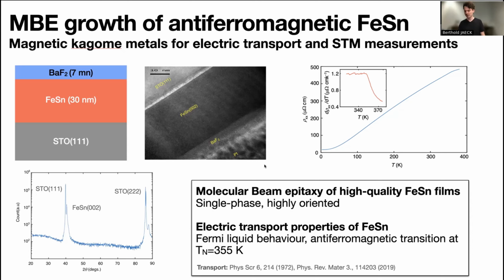At a very fundamental level, when we make a simple Hall-bar device and first study the longitudinal conductivity, we find that this material behaves like a fairly good metal with a reasonably high residual resistance ratio, and we can also pick up the antiferromagnetic transition at the Néel temperature at about 355 Kelvin. Without going too much into the details of these materials characterizations, we find that both the basic electronic and magnetic properties are very consistent with the various works that have been published on this compound over the past years.